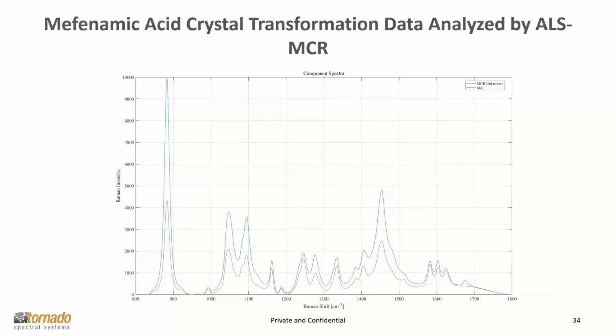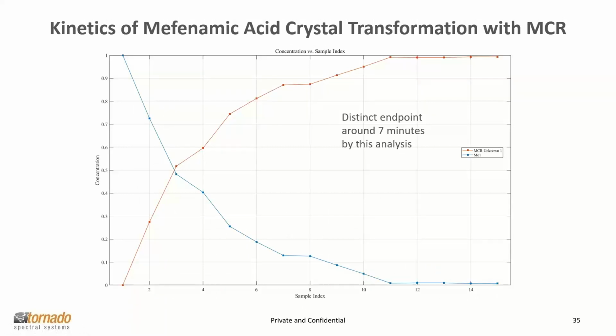Another way to look at the data is by a technique called alternating least squares and multivariate curve resolution, and that's what we're doing here. You can see the two plots, the initial form 2 is in blue. The multivariate curve resolution allows us to pick the data apart and see the differences that may occur between form 2 and form 1. And so you can see the carbonyl band, which is very obvious over here, but there are some other more subtle bands that are present throughout the spectral data that give us an opportunity to look at this a little differently. And we can also follow the trends through that analysis as well.